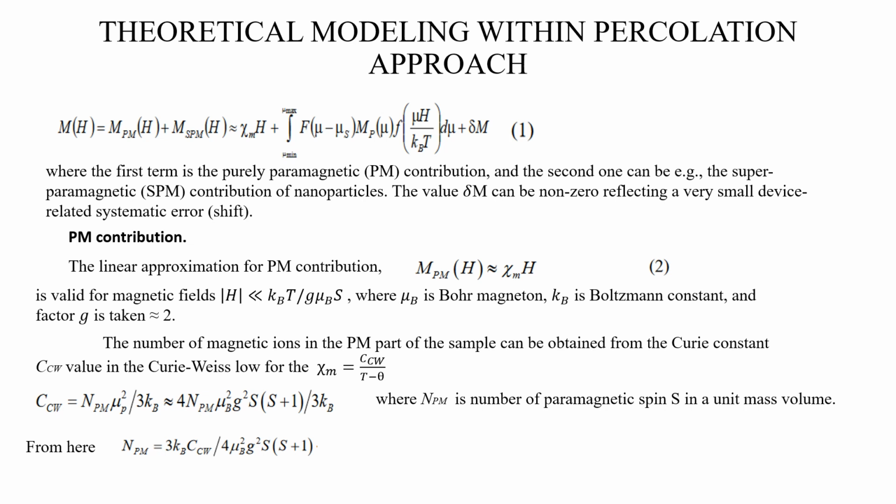The distance between the defects which form the infinite cluster and therefore fulfill the percolation condition or threshold is defined as the percolation radius. To determine the percolation radius, the calculation was performed for nanoparticles of different sizes to ensure that the percolation condition is actually fulfilled. In this case, the ratio between the number of magnetic defects in the infinite cluster and the total number of magnetic defects in the system remains unchanged in particles of different sizes.